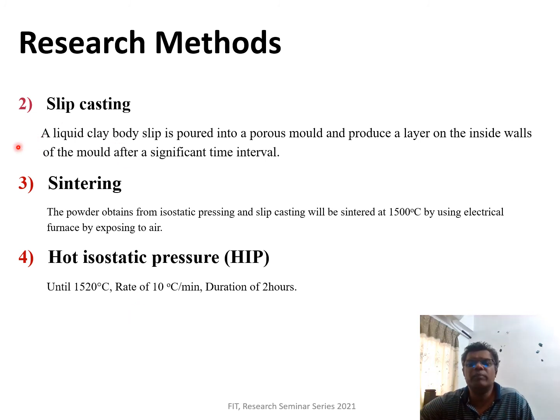Then the important process in the colloidal method is slip casting. A liquid clay body slip is poured into a porous mold, producing a layer on the inside walls after a significant time interval. The powder obtained from the isostatic pressing and slip casting will be sintered, a type of process which is used to densify the substance, by using an electrical furnace. After that, hot isostatic pressing at about 1520 degrees Celsius at a rate of 10 degrees Celsius per minute will be used to further densify the green body.